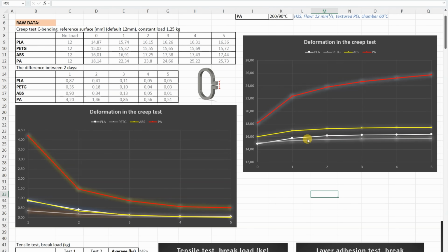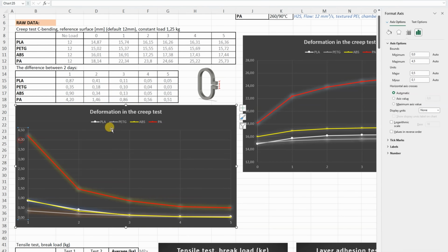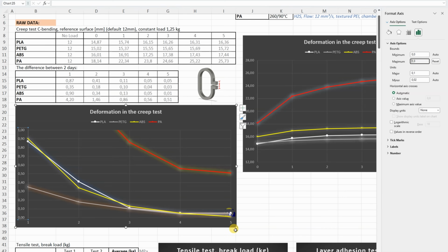But actually the creeping we can follow on the second graph. Difference between 2 days is presented here, and of course we can see the biggest creeping on the nylon. This is what I was familiar. And here, let me change this a little bit and then we will see better what's happening here. And look at this, on day 5 the smallest deformation is from the ABS, and between these 3 biggest on the PLA. And on a little bit higher temperatures this PLA creeping would be even much bigger.